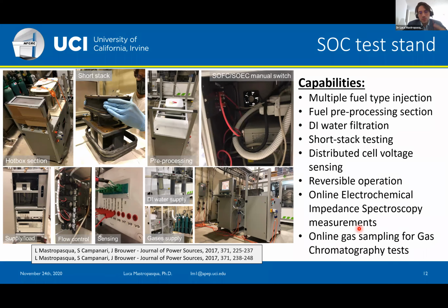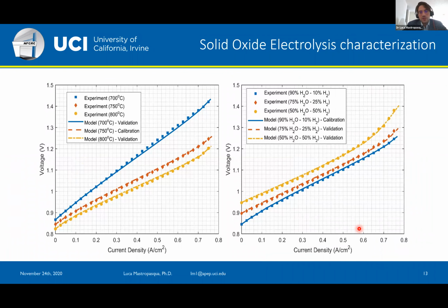So the first thing that we usually do is to characterize the cell or the stack. We perform characterization of these cells using chronopotentiometry and electrochemical impedance spectroscopy at different conditions. On the left-hand side, I've reported the polarization curves at different furnace temperatures. And on the right-hand side, we change the gas composition of the stream that we supply at the fuel electrode. So we first characterize the system, and we support all these experimental data with modeling activity. You can see how we usually calibrate the model on one of these polarization curves, and then we perform a validation trying to understand if the model can predict the other two curves.